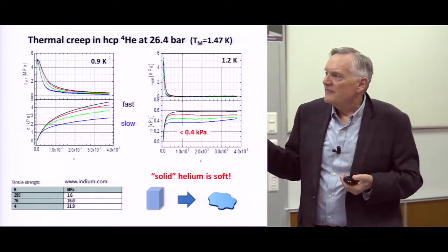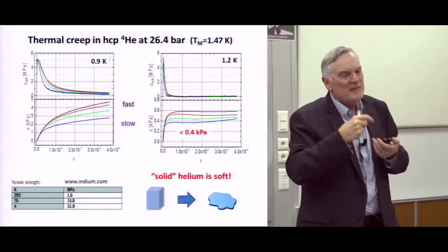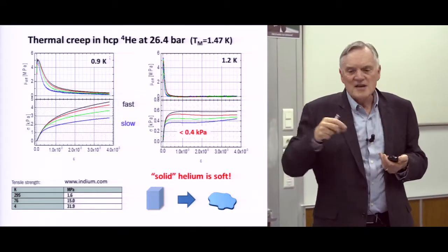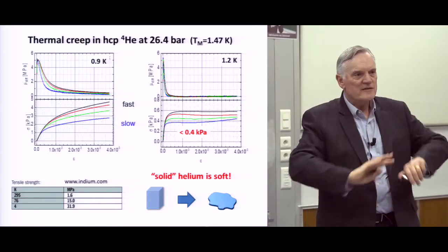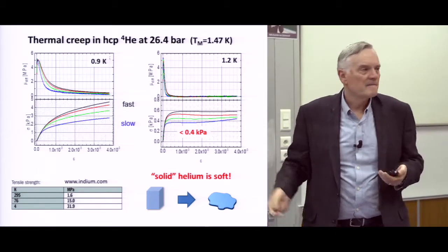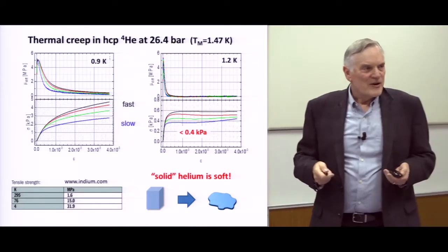when you get up anywhere near melting. So if you had a little cube of helium, if you didn't have to keep it in a pressure cell and keep it pressurized and hold it in place, if you were able to take that and set it down, it would just, under its own weight, turn into a puddle quite quickly, because it's got very, very easy flow when you're anywhere near melting.